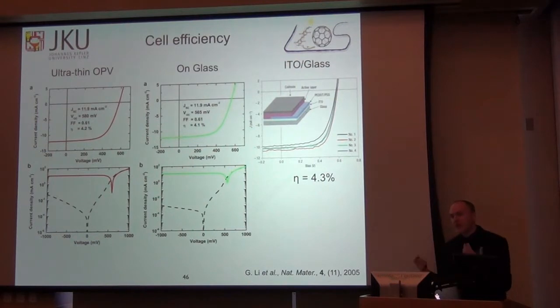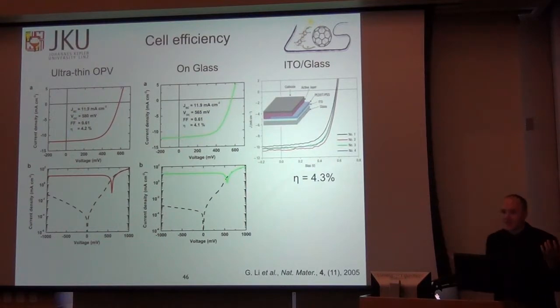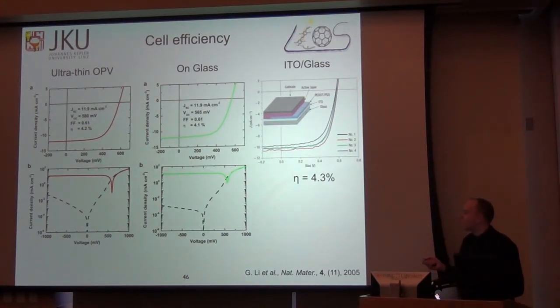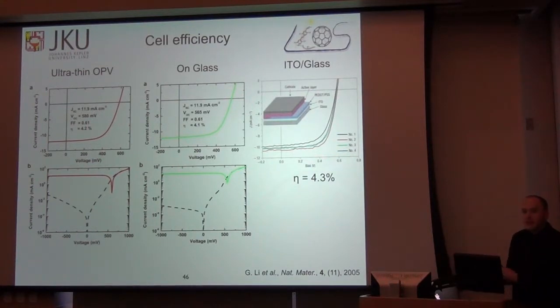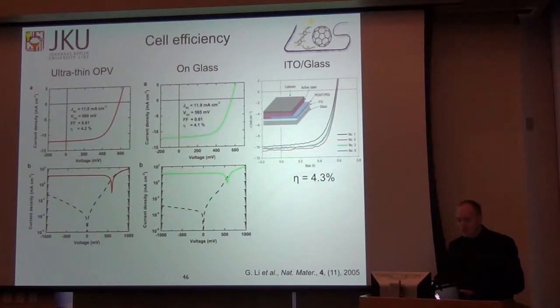And the first question is, does the substrate itself affect the performance of the solar cell? And you would hope that it doesn't, because it's just an insulator that holds things together. And in fact, it doesn't. If you build the devices on glass or on ultrathin foil, you wind up with basically a 4% efficient solar cell either way. And if the devices are small enough, resistance in the PEDOT layer being the limiting factor, the devices are essentially the same performance as you would get on ITO-coated glass too. So there's not really much difference in terms of performance.